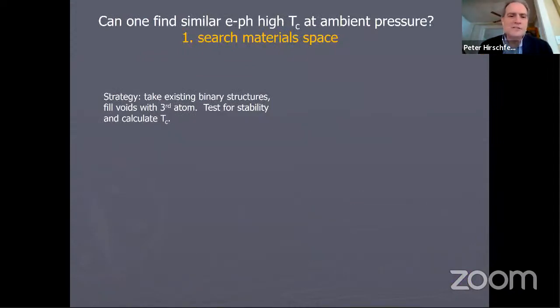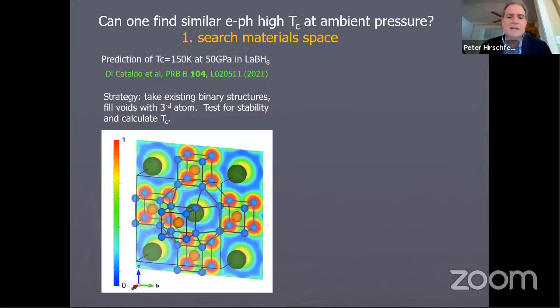One is to take binary structures and hydrides that have been discovered already and researched fairly exhaustively at this point, and fill voids with a third atom. And then you test for stability theoretically and calculate TC. I should have mentioned earlier that one of the unique things about the H3S discovery, hydrogen sulfide, is that it was predicted theoretically by an ab initio calculation. And that's not normally the way new superconducting materials are discovered. In the past, it's always been rather serendipitous. But in this case, it was actually a prediction, and Eremets went out and measured it and found the superconductor.